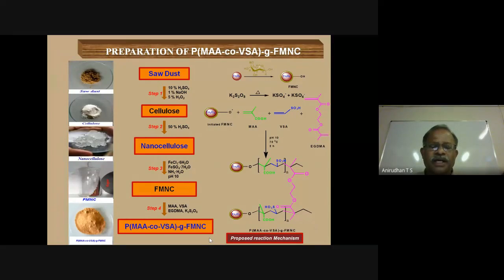I have already mentioned earlier, cellulose is converted into nanocellulose after breaking the amorphous phase, because cellulose contains both amorphous and crystalline phase. The amorphous phase may disappear after treating with 50% sulfuric acid. So your cellulose is totally crystalline in nature, and with further treatment with iron, ferric chloride, ferrous sulfate, you introduce Fe3O4 as a magnetic material. So you can introduce this iron oxide into the cavities of this nanocellulose. So your material becomes a magnetic material.